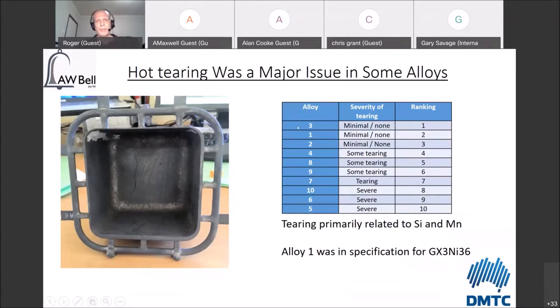Now, just going back to the earlier slide where I talked about the effect of chemistry, if you remember, alloy 1, 2, and 3 were to investigate the role of carbon. So we can also say that the carbon content actually had very minimal effect on the hot tearing. It was the other elements, the silicon and manganese, that were especially problematic for this issue. And so we were able to identify pretty quickly that silicon and manganese were the culprits.